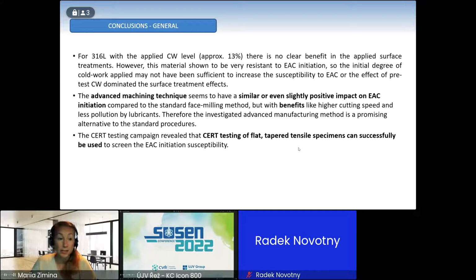And the significant result, I think, is that the constant extension rate test revealed that testing of tapered specimens can be really successfully used for the screening of the EAC initiation susceptibility.